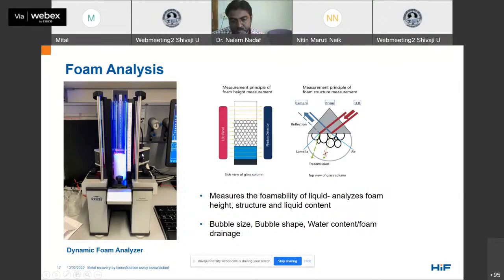You can see there's a camera behind here, which is used to record the foaming process, and a few images from these videos were selected at specific intervals and analyzed with ImageJ software to obtain the information about various properties of foam, like size, shape, and water content. So we did this foam analysis experiment for all the rhamnolipid solutions, like rhamnolipid alone, only with gallium, or both gallium and decanediol, or only with decanediol. So now I would like to show you the results of this foam analysis.